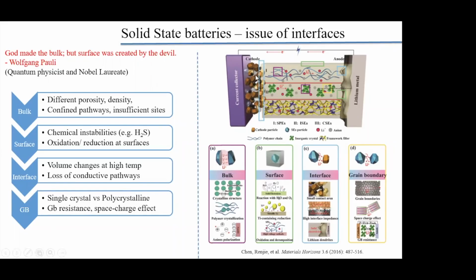And then at the surface level, you have chemical instabilities. These interfaces need to match up chemically also. If they don't match up chemically, if one of them has a tendency to undergo oxidation or reduction at the surface, then that's not good. For example, sulfide-based solid electrolytes have a tendency to release H2S gas, which is not good. And that is at the surface.